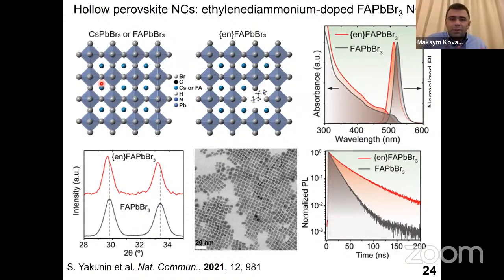Let me show you another aspect which is possible with perovskites and not easy to do with anything else, which is that now you can also engineer the perovskite itself. The perovskite lattice is very soft. So you can actually displace some of your inorganic constituents with organic ones, maintaining the lattice. So the lattice will not collapse, even if you displace up to 10% of the core material by another organic material. And so you can keep the nanocrystal size, but you will drastically modify the electronic structure.